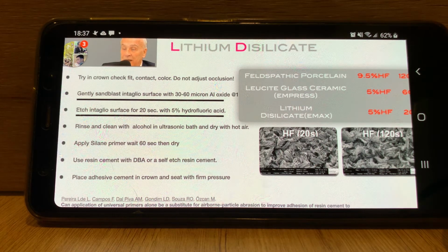I must point out that with some things like lithium disilicate, you can see in the literature that with more concentrated hydrofluoric acid or longer etching times or both, they do seem to get better shear bond strengths. However, they do give up something in the flexural strength of that material. That is the reason that the manufacturer recommends this concentration and this etching time, because probably it is a kind of compromise between adequate retention and reinforcement of the material, and yet not weakening the material itself.